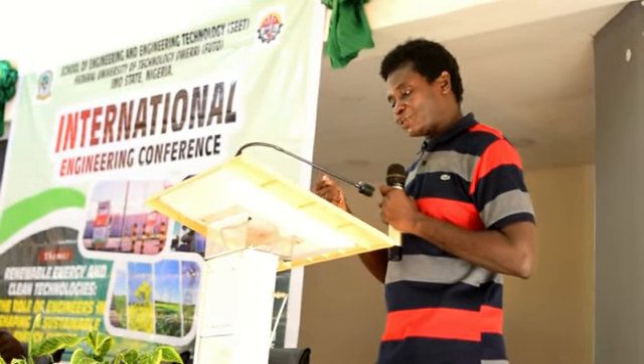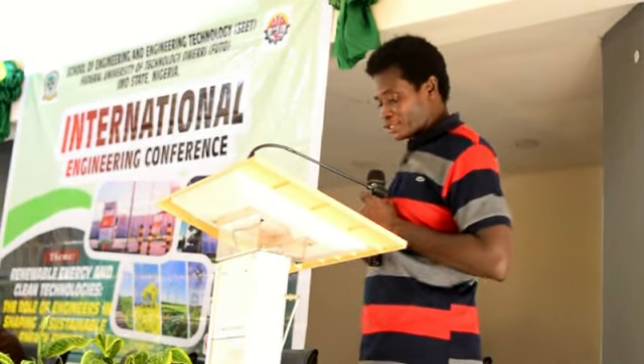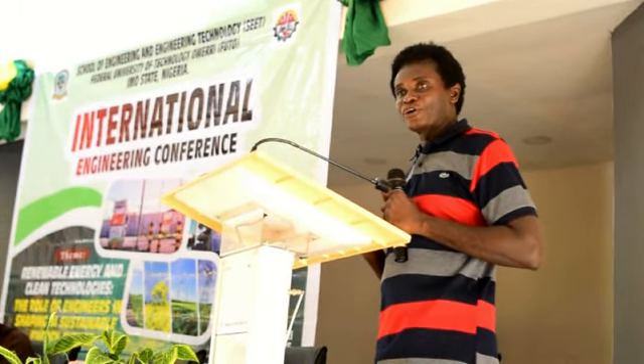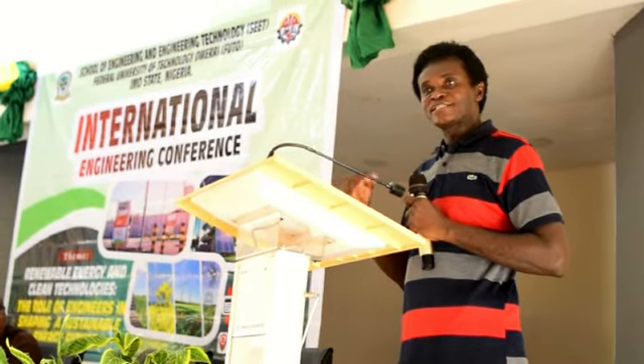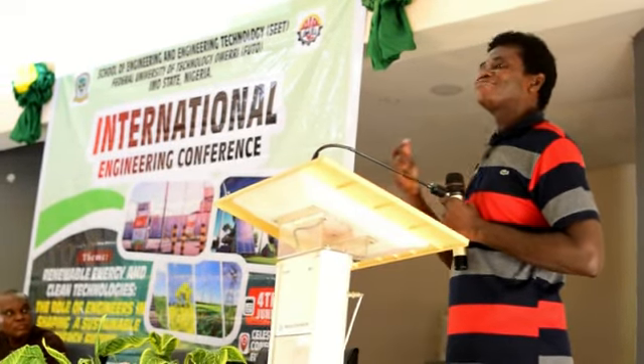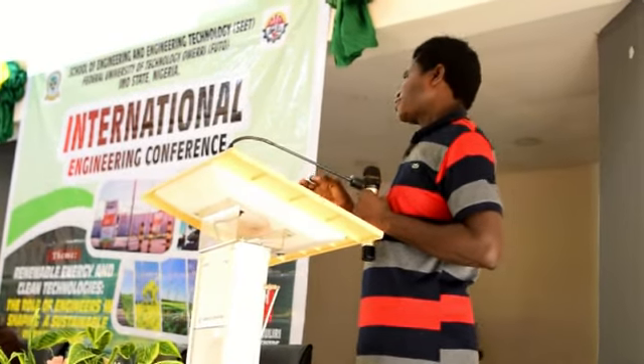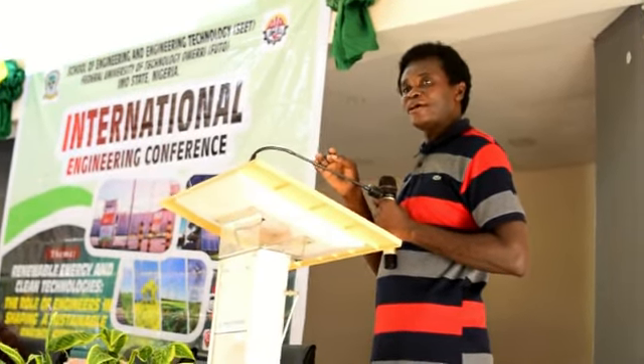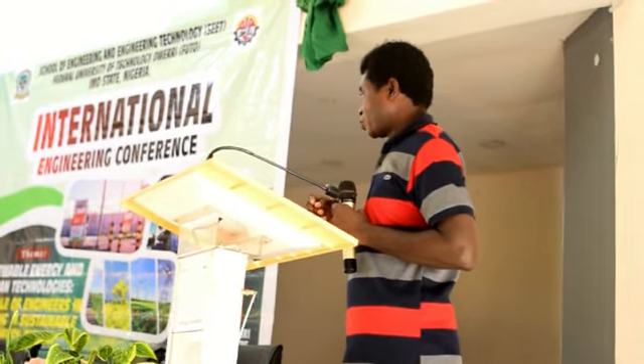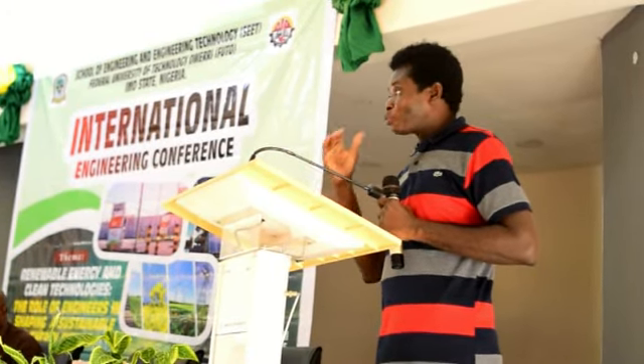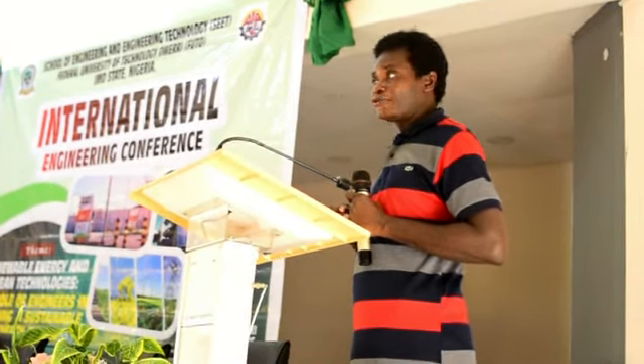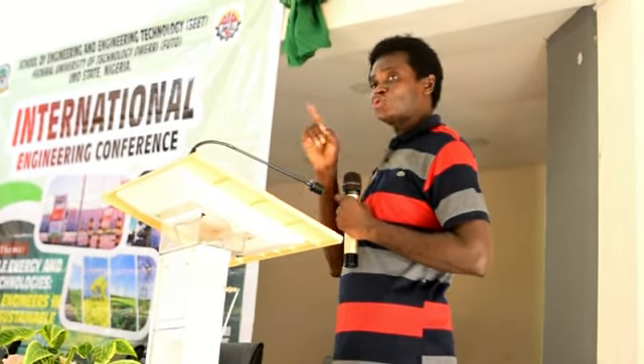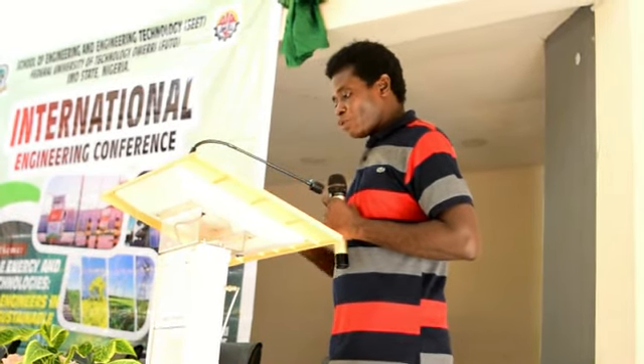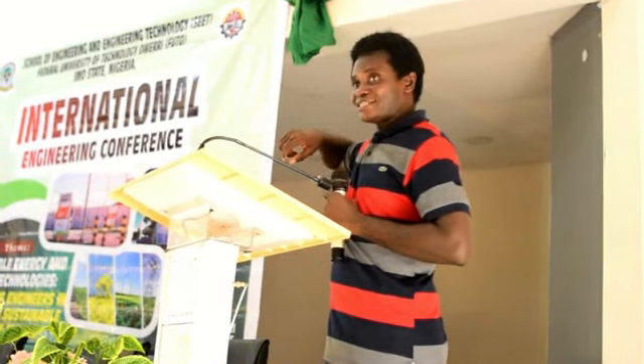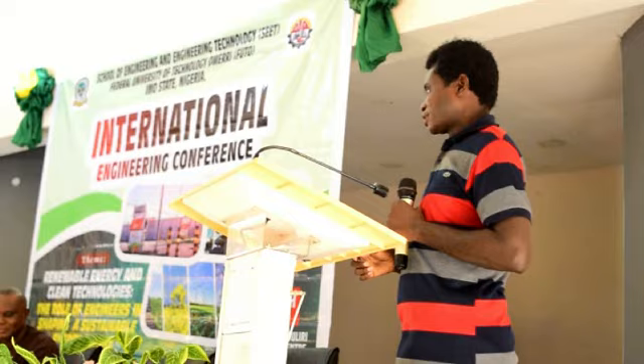Now, if we go further to the end, you can see that for 2.6 gigahertz, if you compare the SAR with the 700, you see that the SAR has increased. Earlier I mentioned the FCC and ICNIRP standards. The FCC gives a 1.6 watt per kilogram standard, so any device produced should not be producing more than that for FCC regulation. ICNIRP regulation is 2 watt per kilogram. So when we look at all the SAR values there, you can see that they are all within the standard, and these cannot cause any form of harm.